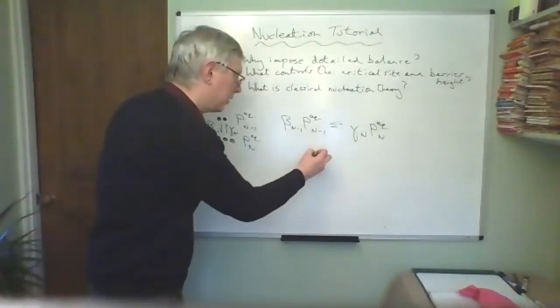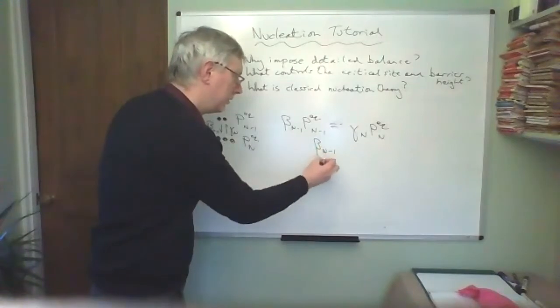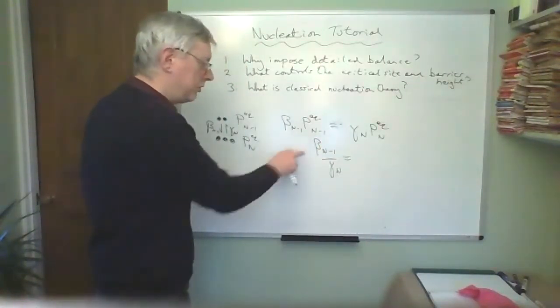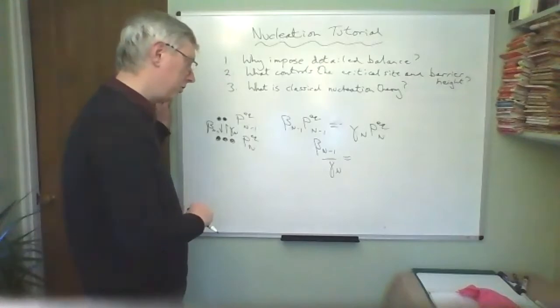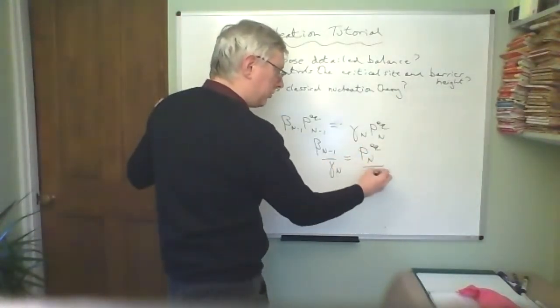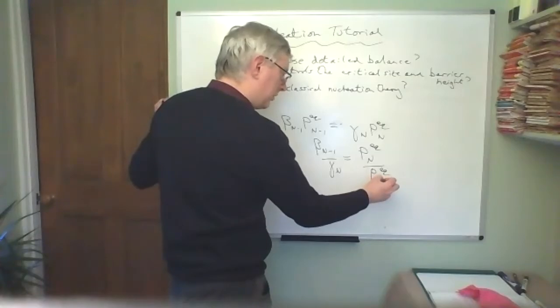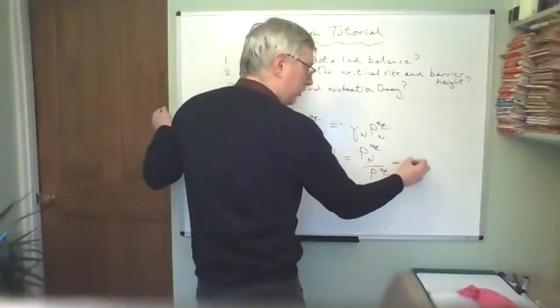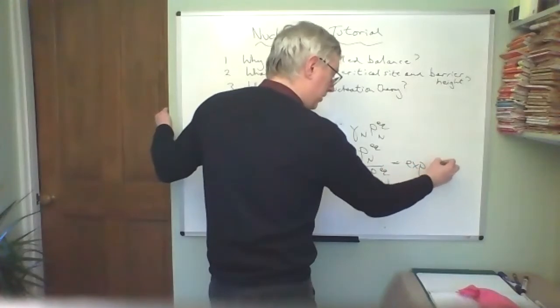This is useful because the ratio, and again, I'm just repeating what you just said, the ratio of these coefficients of up and down rates is a ratio of equilibrium probabilities in the grand canonical ensemble, which refers then to a difference in availabilities.